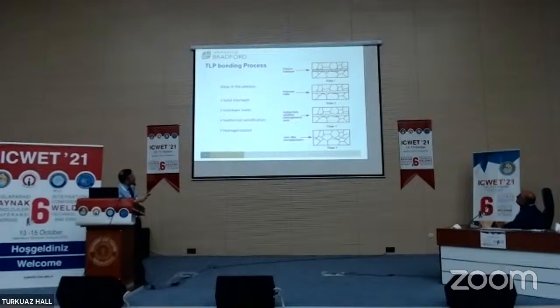So we start off with a solid interlayer, and this interlayer will melt. Either it's the melting point of the interlayer, or it's the eutectic point that forms between the interlayer and the base metal. And then if we hold at the bonding temperature for a certain length of time, diffusion mechanisms will encourage isothermal solidification. And normally there is a last step process which we call homogenization, and this usually involves some kind of grain growth across the joint, or at least a uniformity in diffusion processes in that joint region.